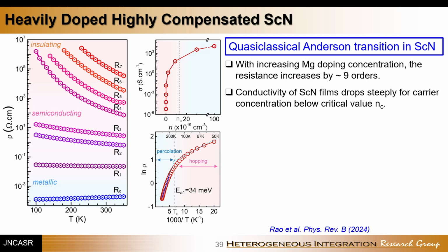So we start doping scandium nitride with magnesium 2 plus. As you see, this is resistivity versus temperature when the hole doping is very low. In other words, when the hole doping is very low, the resistivity is very low, and the resistivity increases with temperature, sort of like a degenerate semiconductor or metal. As you keep on adding more and more hole doping, the resistivity keeps on increasing. And at the highest carrier compensation level, you see 8 to 9 orders of magnitude change in resistivity.